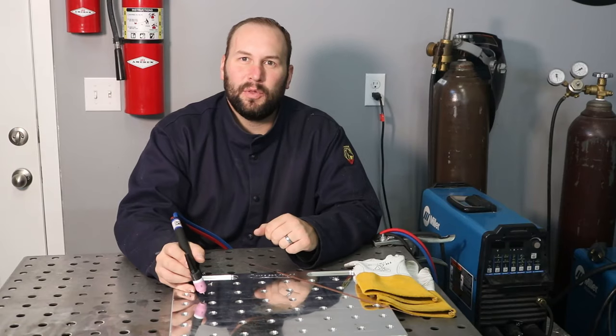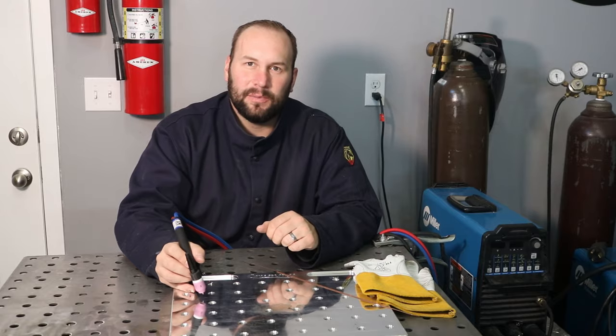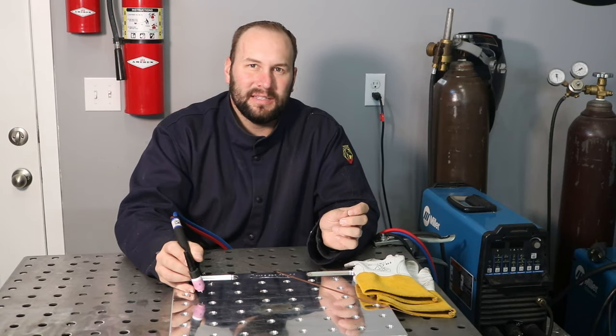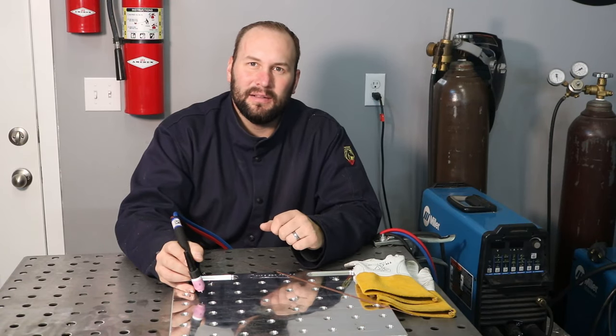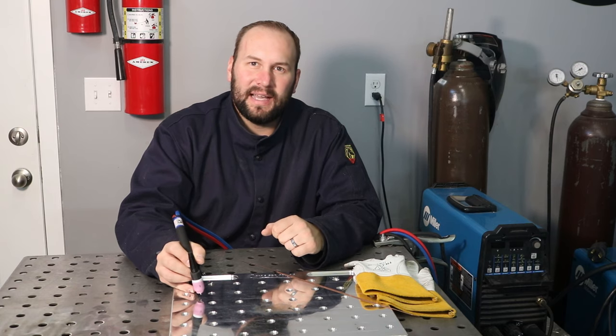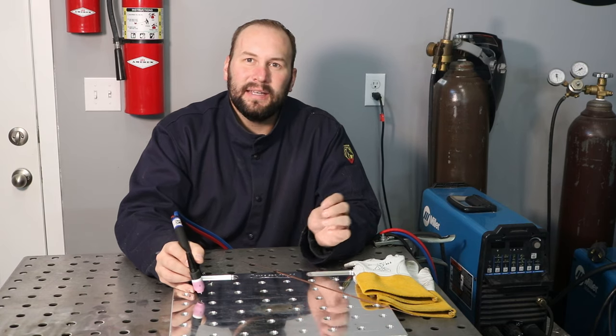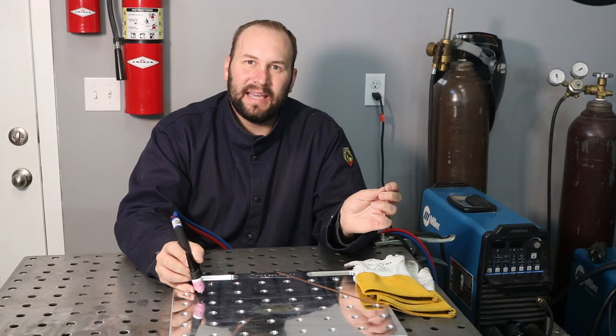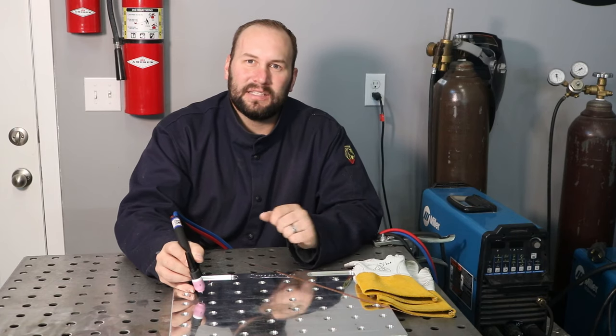And the interesting thing about this is it has more to do with what I'm doing with the torch than with the filler metal. Because if you look, I'm holding a long arc, and I'll show this again. I'm holding a long arc here, and a little bit too much torch angle, and then I put my filler metal down, and it's melting before I get it down into that puddle, right? If I'm keeping that nice tight arc and my angle right, then it's pretty easy to just get your filler metal right in the right spot.